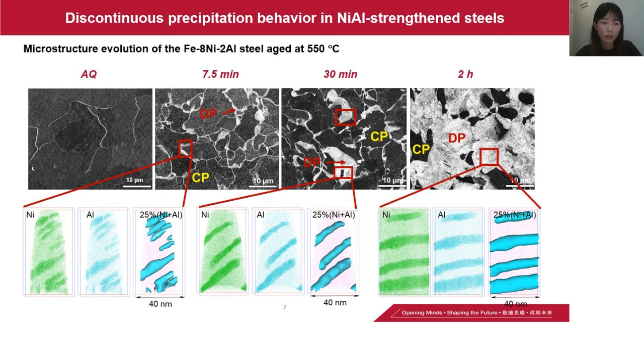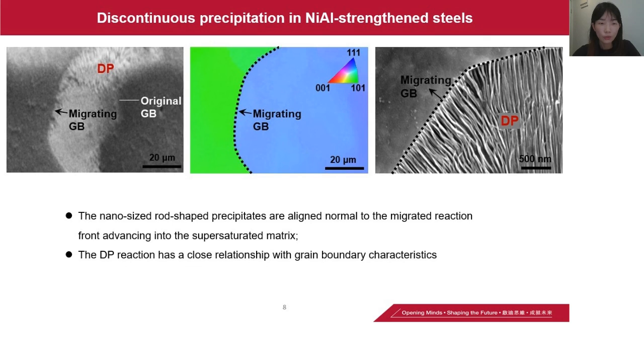But to deeply understand the characteristics of the discontinuous precipitates, we performed atom probe tomography experiments. From the atom maps and the isosurface of the precipitates, we can see that the discontinuous precipitates are rod-shaped and aligned parallel to each other, and the precipitate radius is less than 10 nanometers.